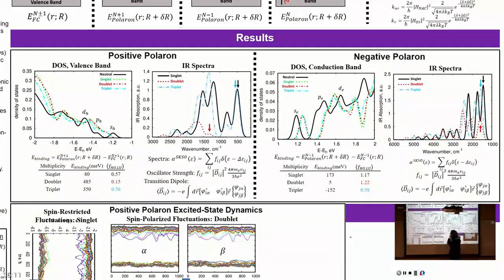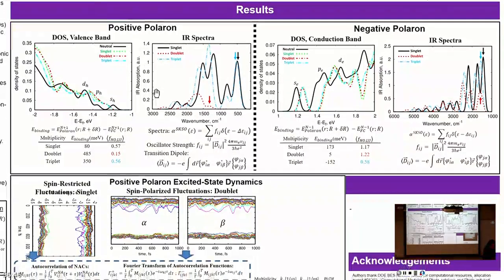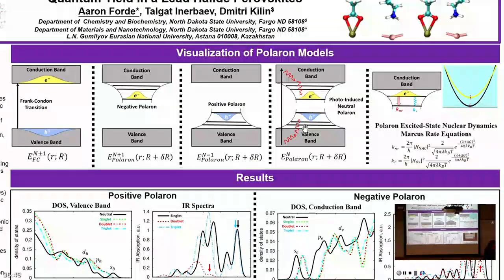For the singlet and the triplet anyway, they have about the same absorption onset peak. And those are only electronic transitions, because in the real experiment they can be intermixed with surface vibrational transitions, which are also in this range, like 1500. Yes, for any organic there will be a strong peak. So these are just electronic state to state transitions in the potential well.